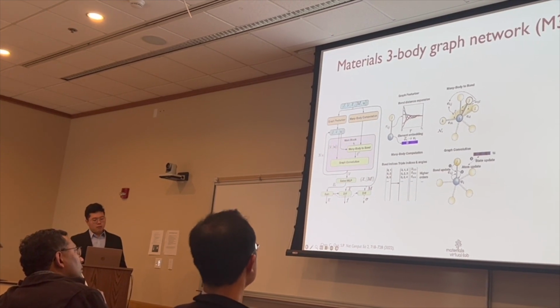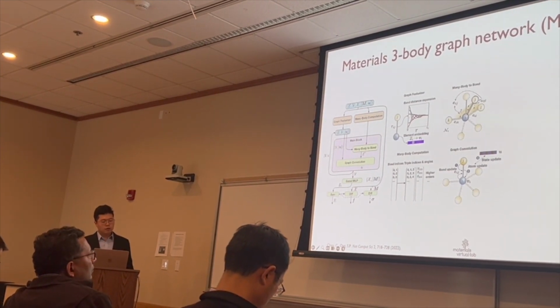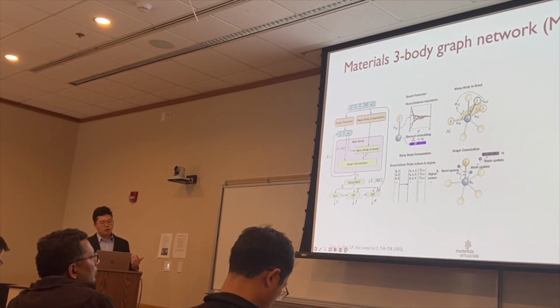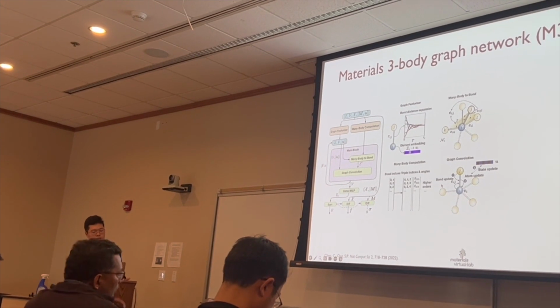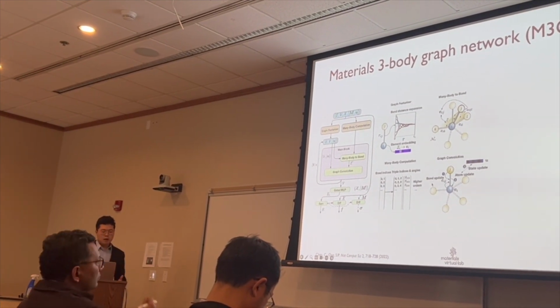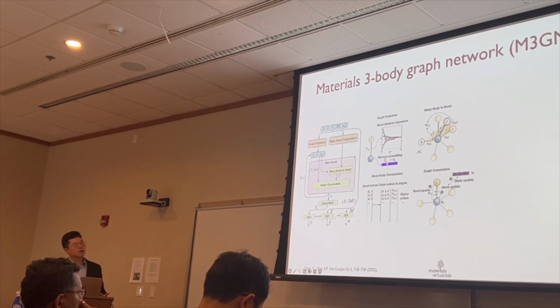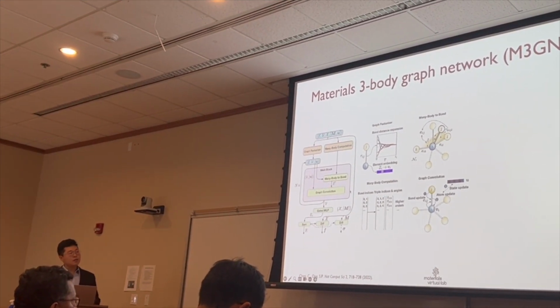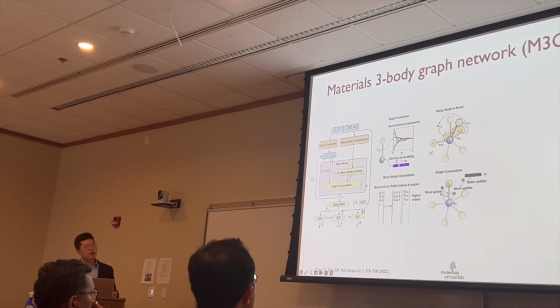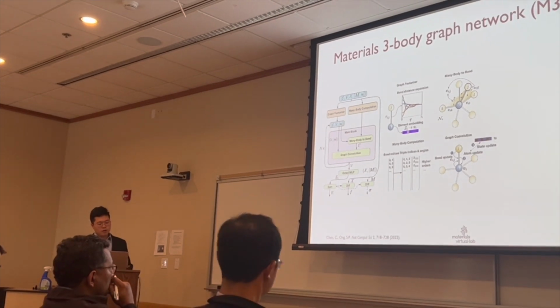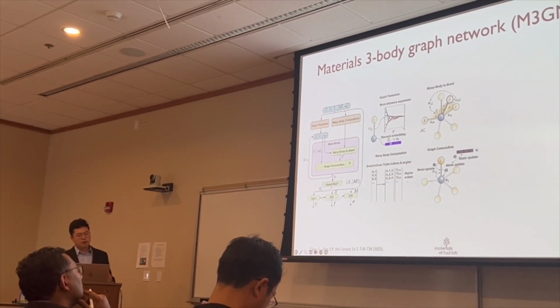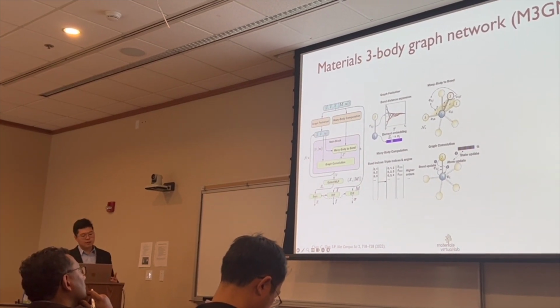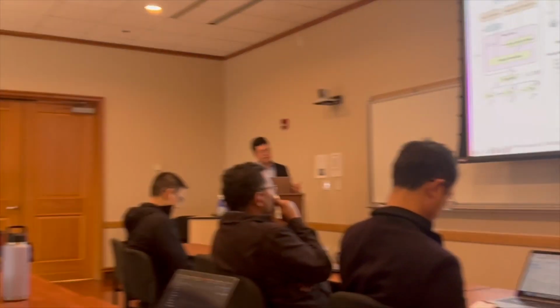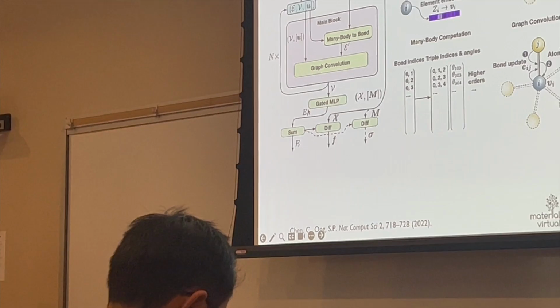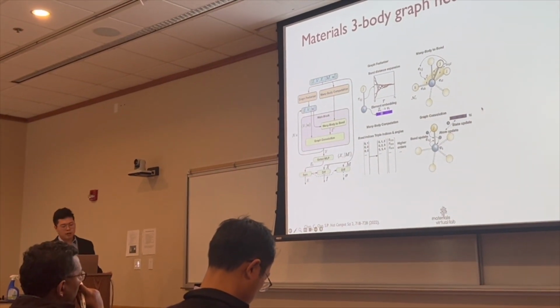And in the main block, we perform many-body to bond and graph convolution operations to sequentially update the bond features and atom features, and optionally the global state features, so that after n cycles of this main block operation, the atom feature of this M3GNet model can incorporate the information of interaction with its neighboring atoms within n times the cutoff radius used during the featurization step. After that, these atomic features are used to predict the atomic energy, whose summation equals the total energy of the system, just like all the other machine learning interatomic potentials.